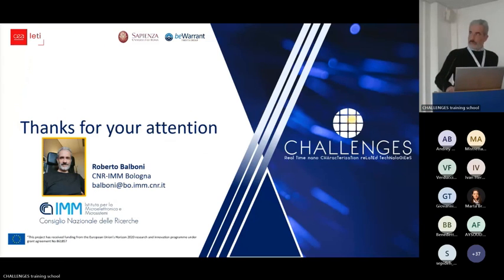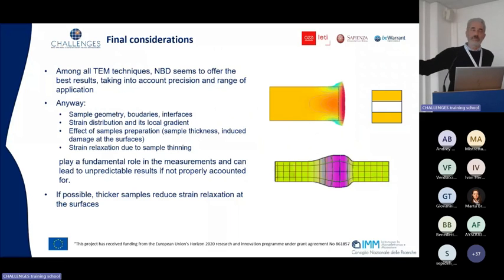But in conclusion, you must keep in mind that sample geometry, the strain distribution, the effects of sample preparation, and the strain relaxation due to sample thinning have a fundamental role in this kind of analysis. The final message is that you can use even the best technique possible, but it can be a perfect technique in a given kind of sample and lead you to a bad result in another one. You have to know what you are actually managing.